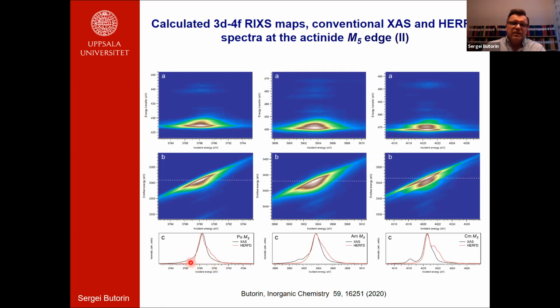And then we know that high spin states actually tend to scatter elastically, or to states with low energy transfer, while low spin states tend to scatter inelastically. So in the case of high spin states, they will have reduced inelastic scattering weight, which we actually observe here.